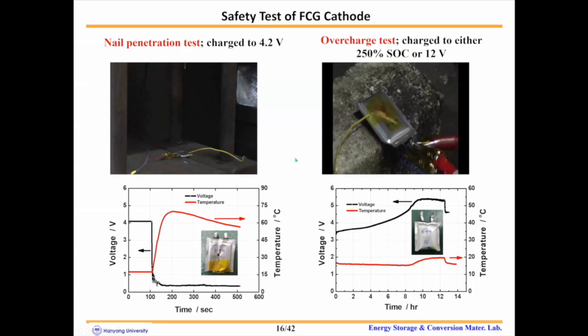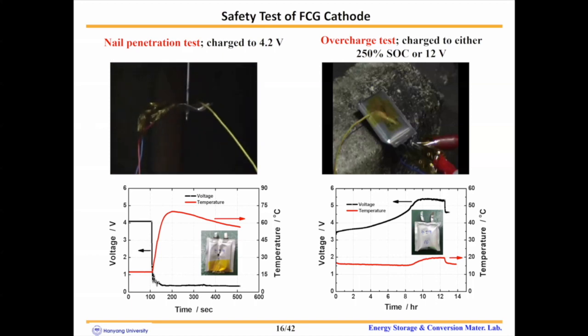We did a safety test. One is the nail penetration, the other is the overcharge test. We fabricated pouch type cells in our laboratory using the synthesized FCG cathode with a capacity of 250 milliampere hour. And then after fully charging to 4.2 volt, the nail was penetrated. After the nail penetration test, the highest temperature of the cell was 70 degrees Celsius.